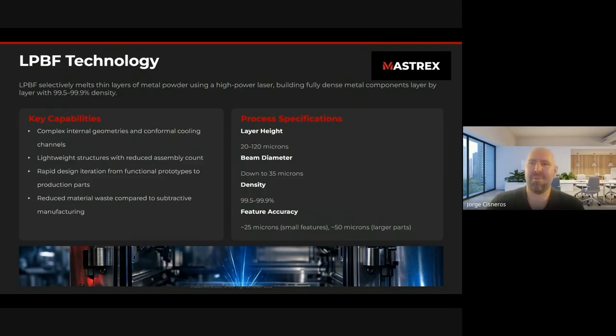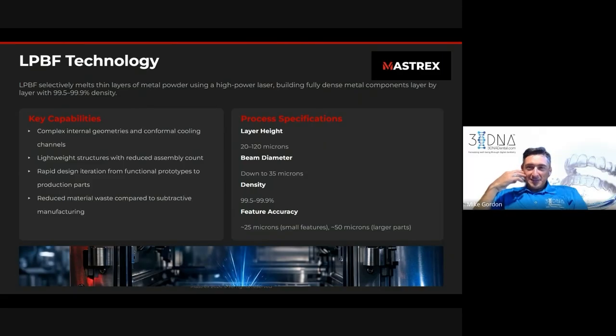Yep, that is directly off the printer. Typically it is 99.9%. We drop it down to that 99.5 because that's all some people need in dentistry, and most parameters we use are always that maximum density, which is really nice because compared to traditional methods such as a raw material that you're milling or even casting, there are more pores and inclusions, meaning there's slightly less mechanical property. Which is amazing. I don't think that, in the past at least, metal 3D printing has had the reputation of making extremely strong things, and I think that's been a misnomer for a long time. So I wanted to focus on that a little bit.